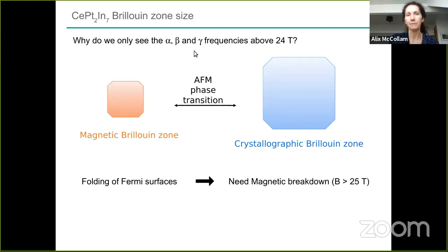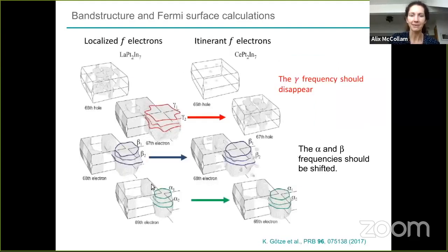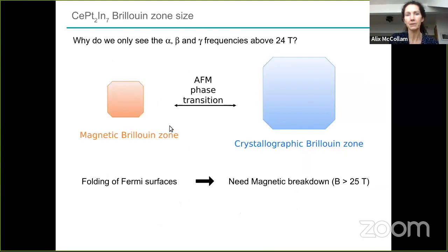In fact, we're looking at the system in an antiferromagnetic phase. This isn't calculated specifically to be antiferromagnetic. And in fact, the magnetic Brillouin zone is smaller. But when you reach a certain magnetic field, you get magnetic breakdown between the orbits, folding of the Fermi surfaces. But you can jump with magnetic breakdown through those folded parts of the Fermi surfaces, and then you see the regular orbits that you would see in a paramagnetic system. I don't show the calculation, but it's a straightforward calculation of what the magnetic breakdown field would be, and this should be about 25 Tesla or above in this material.